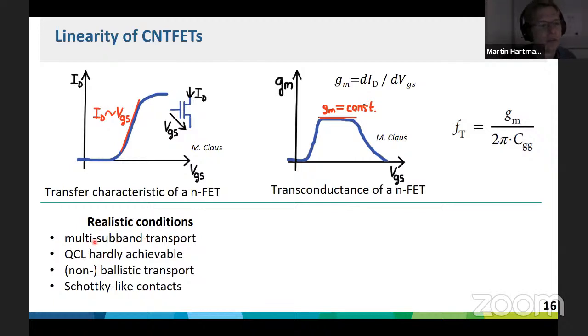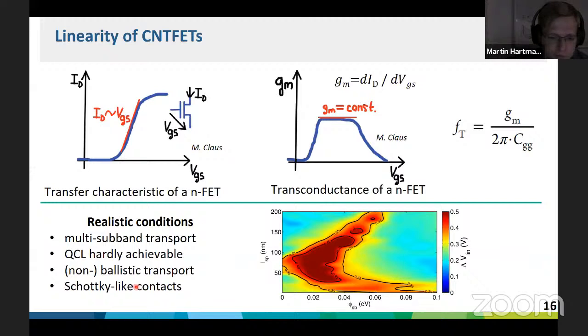You usually don't have just single subband transport, you have multiple subband transport. The quantum capacitance limit is not that easily achievable, and you usually have some Schottky-like contacts. So the guys from TU Dresden, they took this into account and they thought, maybe we can introduce a certain Schottky barrier here to avoid a charge backscattering into the source and thereby increase again the linearity. And this was the origin why they started to do the simulations, and these are the results that I've already shown you.